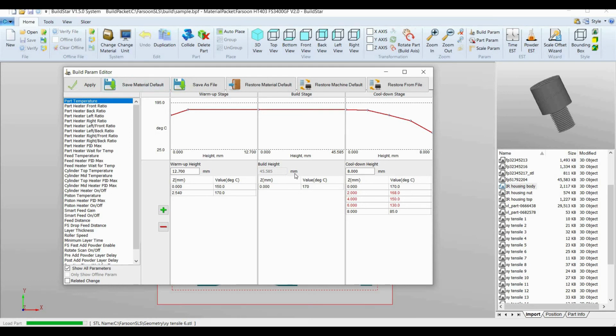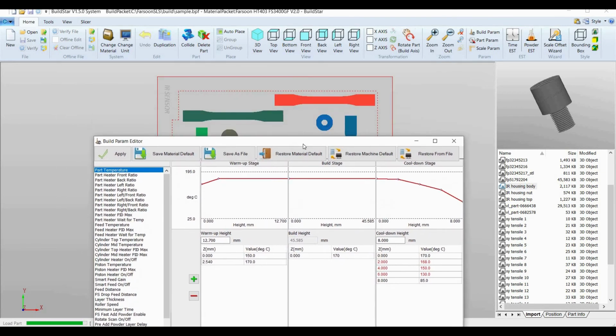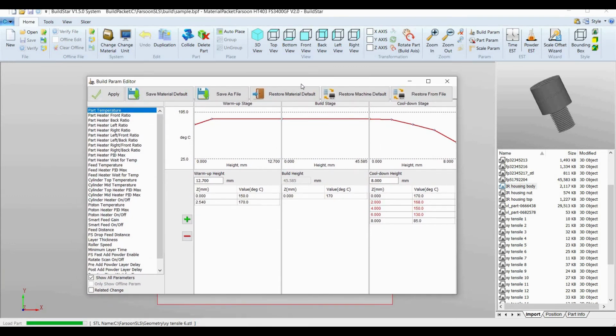Sometimes if you're getting curling, especially early on, right after the sintering process, usually the heaters are taking too long to ramp up, so we can increase the duty cycle to make up for that lost time. If you see melt pool, as discussed in our energy density video, we can decrease the part temperature the same way. Or if we have hard part cake throughout the whole build, this usually means that we're putting too much heat energy into the part bed, so we can lower the part temperature as well to compensate for that.